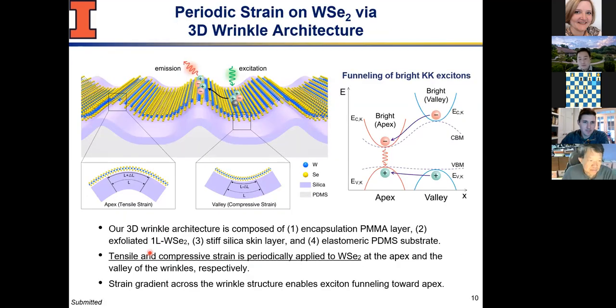So one example I want to share is really trying to use the strain, or I should say strain gradient, to manipulate intralayer excitons. So we're going to deal with just one monolayer. In this case, it's tungsten diselenide, so it's tungsten in the mid-plane, selenium on top and bottom. And I simply created a wrinkle out of it. You start seeing this in a schematic drawing.